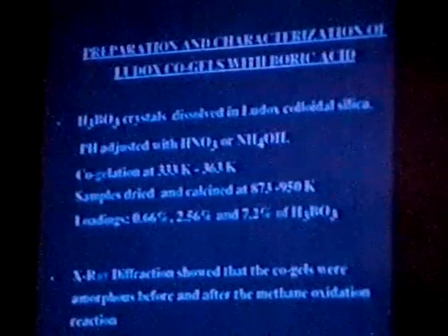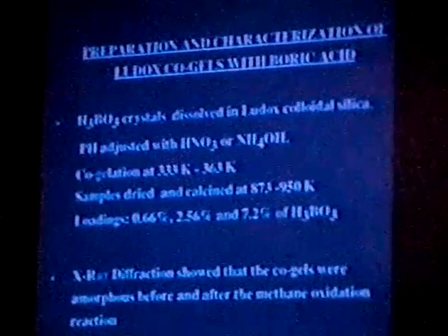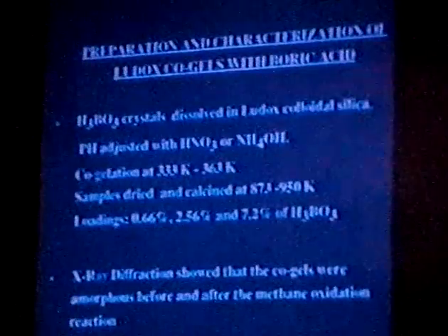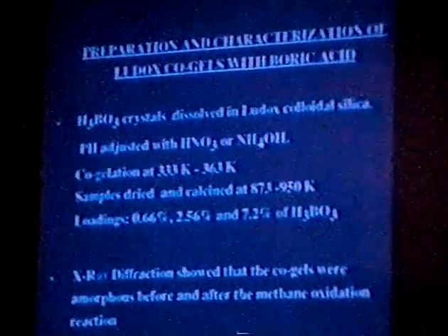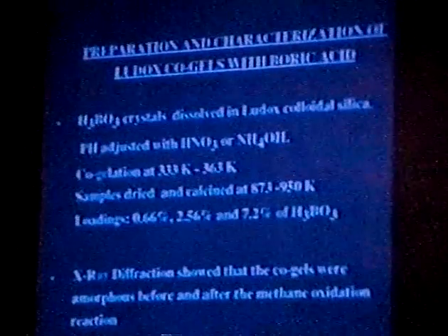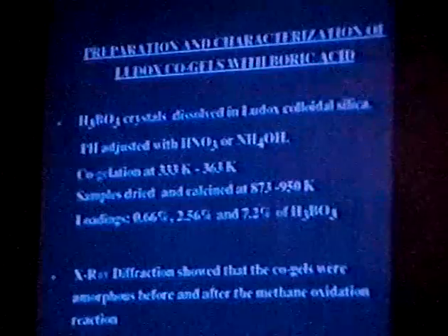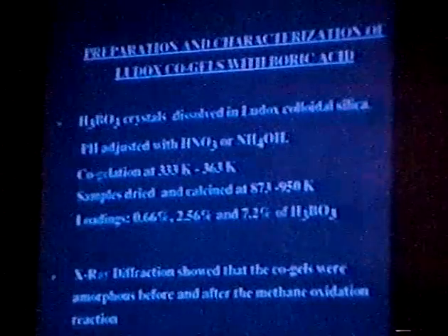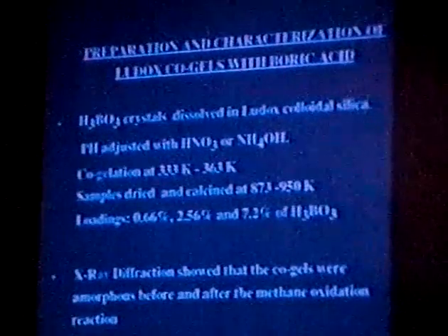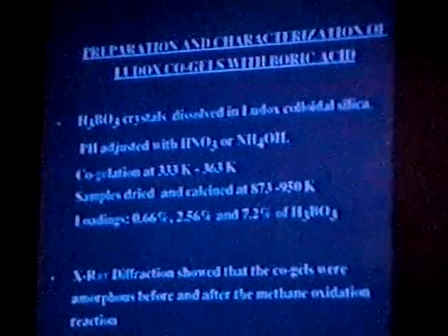We did X-ray diffraction, and we found out that the co-gels were amorphous both before and after the methane oxidation reaction. X-ray photoelectron spectroscopy of both fresh and used catalysts showed boron present in an oxidation state of +3. The chemical environment was very similar to the one in boric acid.